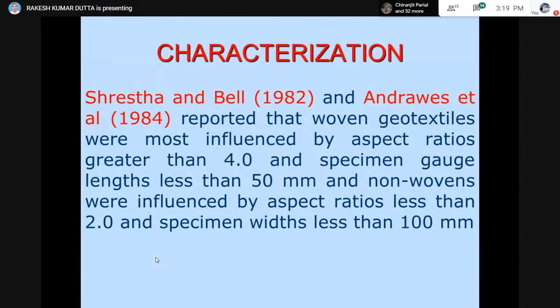Now the characterization work was started long back in the years 1982 and 1984 by two researchers. They picked up polymeric woven geotextiles and studied their behavior, and finally they found that these woven geotextiles were most influenced by an aspect ratio greater than 4. That means if the aspect ratio is greater than 4, their strength is going to be affected, and the specimen gauge length is less than 50 mm. And the non-wovens were influenced by an aspect ratio less than 2 and specimen width less than 100 mm. These were the initial studies carried out by these two researchers using a polymeric type of material.